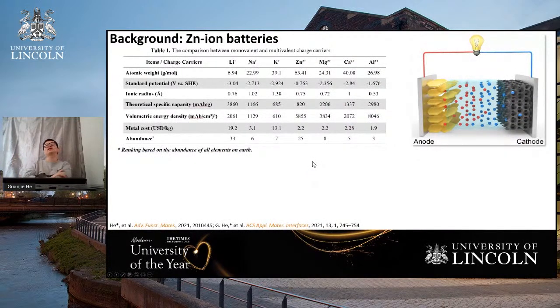Our research focuses on another type of battery, the zinc batteries. Let's first compare lithium and zinc batteries. For lithium ion, the charge carrier is Li+, and the atomic weight is quite light, around 7 grams per mole, which is quite good. Lithium also has a very suitable potential of -3 V versus the standard hydrogen electrode. That means it can give a relatively wide potential range. But to reach this wide potential range, we can only use organic electrolytes. And the theoretical specific capacity and volumetric energy density of the lithium battery are quite high.